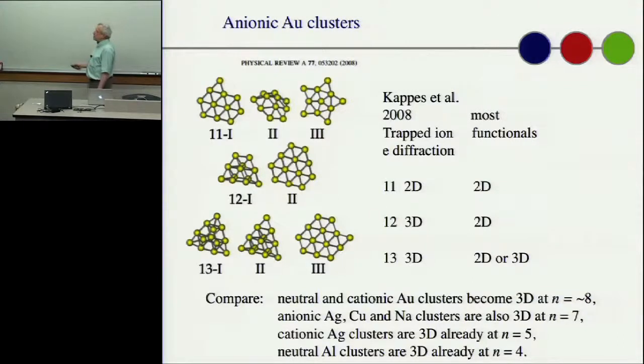And you see you can have 2 kinds of structures. You could have a planar structure, or you could have a 3D structure, which is just another name for a non-planar structure. So Manfred Kappes did these beautiful experiments in Europe. He trapped the ions and he did electron diffraction off of these size-selected clusters. And he found that the border between going from planar to 3D is quite high. It's between 11 and 12.